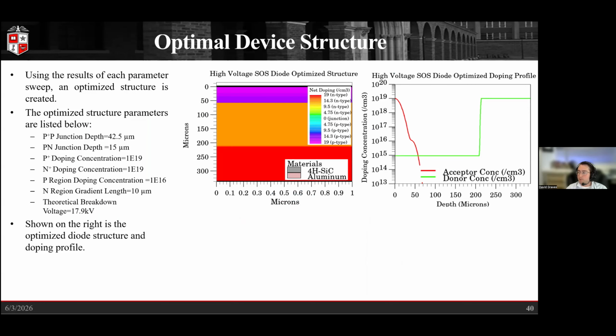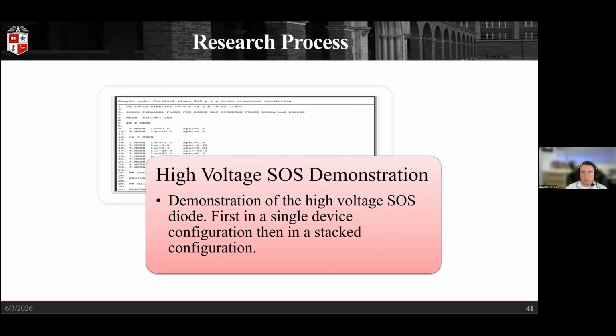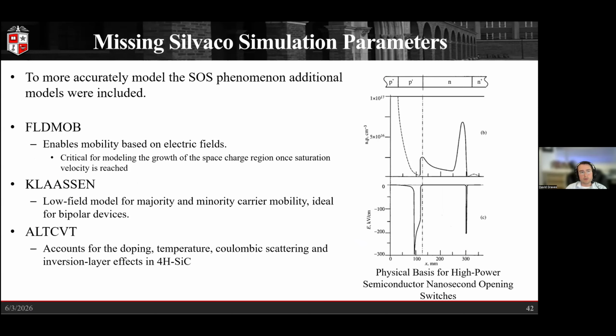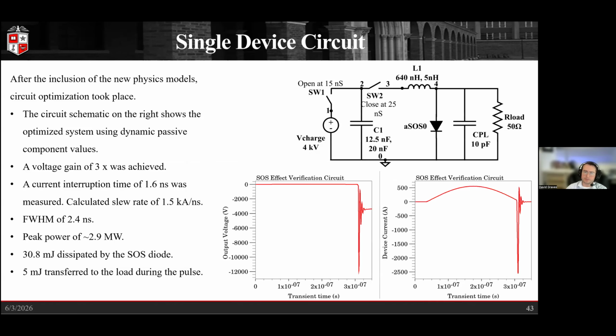So putting all of the information together from the previous slides, we have the figures shown here. And so now we'll look at some of the circuits. So the first thing we did was include some additional models into Silvaco Victory Device, that being field-dependent mobility, the Klaassen model for low field modeling of majority and minority carriers, and Alt CVT, which accounts for the doping, temperature, and Coulombic scattering inversion layer effects of silicon carbide.